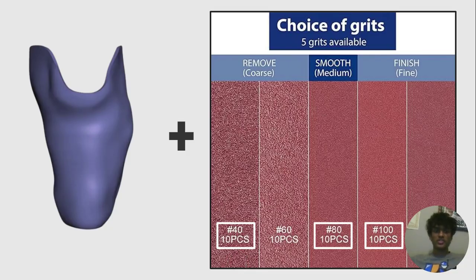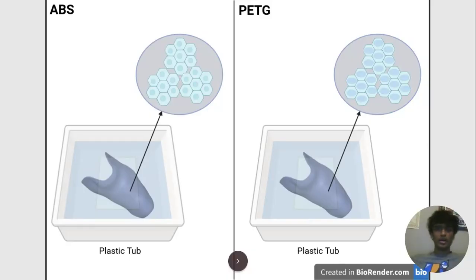An abrasion test was also conducted. Sandpaper grits of number 40, which is coarse, number 80, which is smooth, and number 100, which is fine, was rubbed on 3 distinct parts of the prosthetics, and the mass lost was measured. A water absorption test was also done. Water absorption percentage was measured within this test.